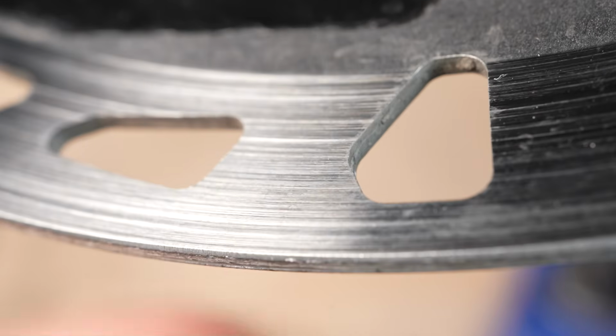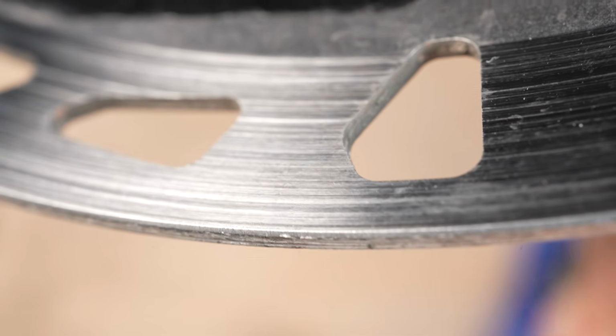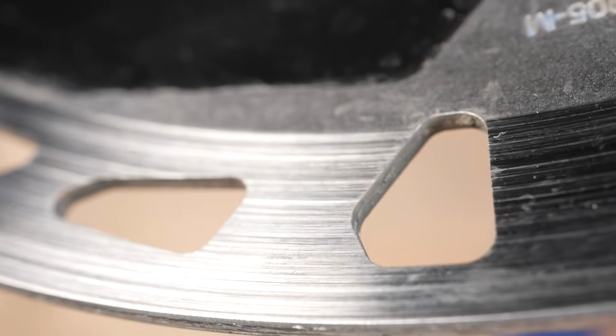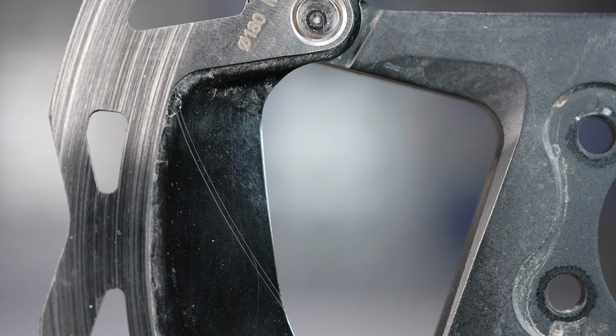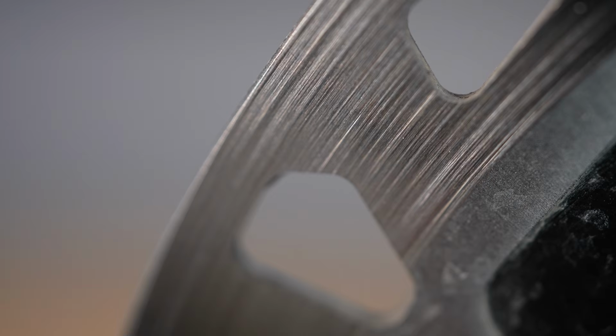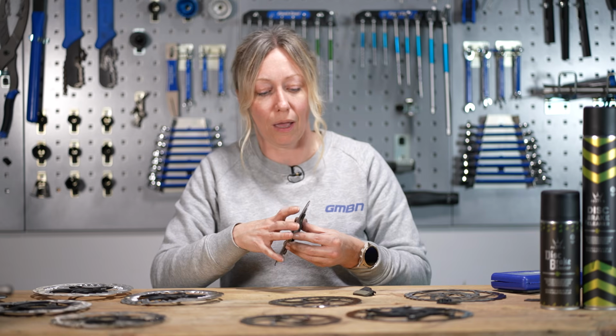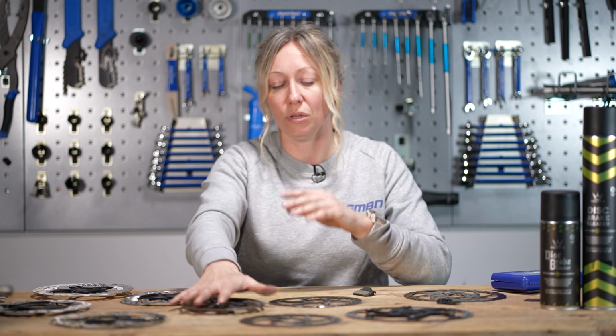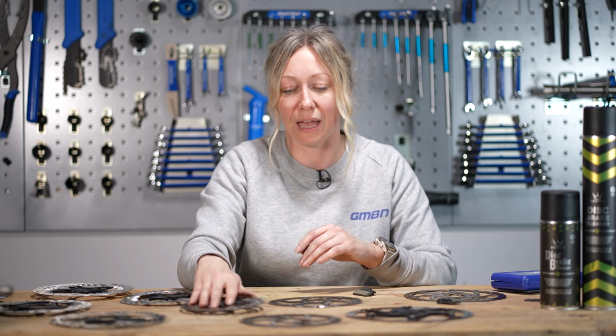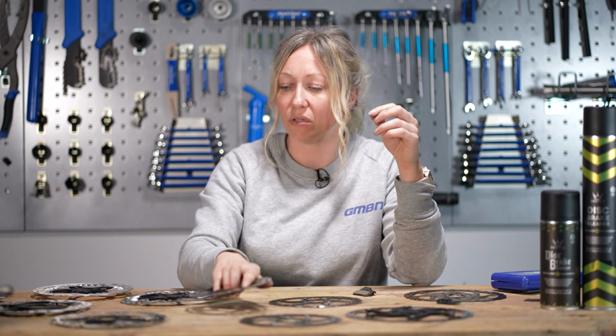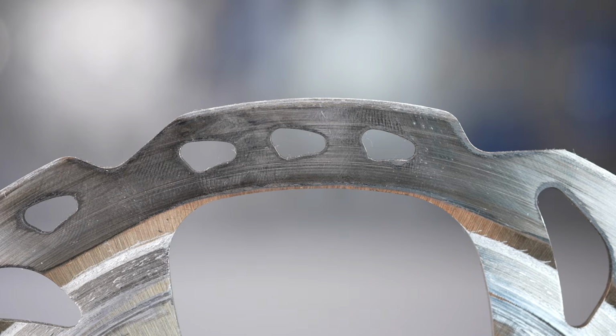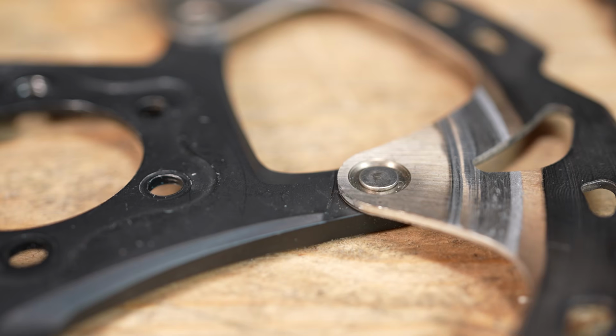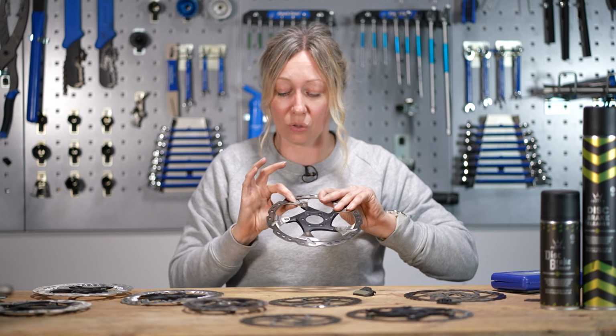Same will happen with your discs. You can get them too hot too quick. In fact, this one, definitely this road disc got too hot too quick, and you can see that it's actually started to have a bobbling effect where the material is melting away. So do keep an eye on your discs for changes like that, scratches, scores. If you get any of these multicolored changes, multicolored tones or blacknesses, that again is from scorching.